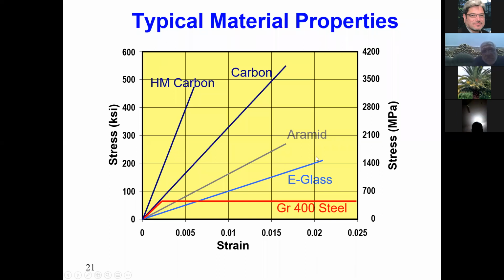The glass fiber has a strength of about 1400 MPa. So about 3 times the yield strength of steel. Aramid has got even higher, about 2000 MPa. The highest is the carbon fiber. The carbon fiber has got a strength of nearly 10 times the strength of the steel. You can see it's nearly 4000 MPa compared to 400 MPa.